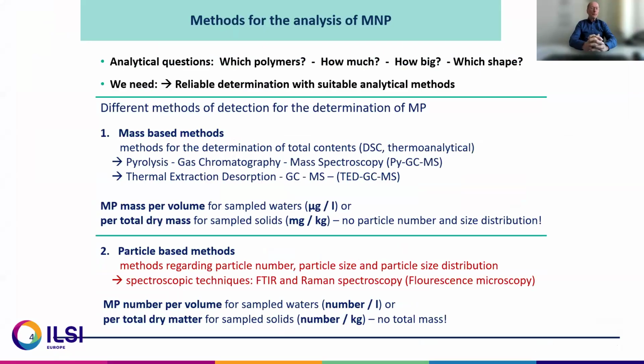The first question is always, if we analyze microplastics: which polymers, how much, how big, and which shape. For all that, we need a reliable determination with analytical methods. In principle, we have two detection methods, the so-called mass-based methods. That means methods for the determination of the total content. This is mostly Pyrolysis-GC or thermal extraction desorption GC-MS. The result is always a mass per volume or a mass per total dry mass. We have no information about particle numbers and size distribution.